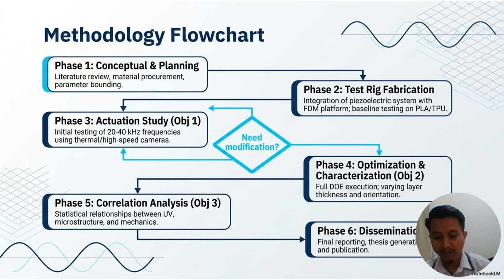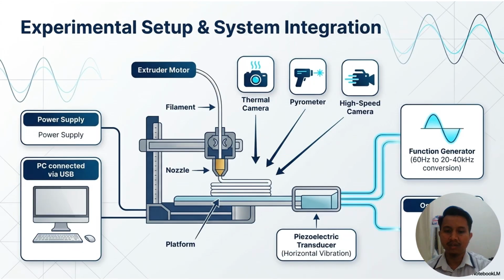Using the optimized UV parameters from Phase 3, we now vary printing parameters, which consist of layer thickness and build orientation, and conduct the full DOE matrix with complete mechanical and microstructural characterization. Phase 5 is the correlation analysis, addressing objective 3, where statistical relationships between UV parameters, microstructure, and mechanical properties are established. Phase 6 is the dissemination, which is thesis writing and journal publication.